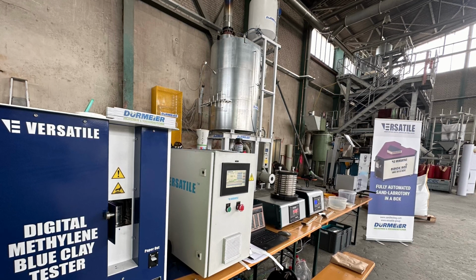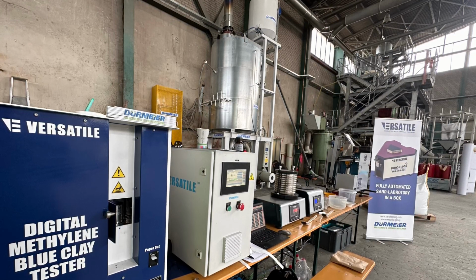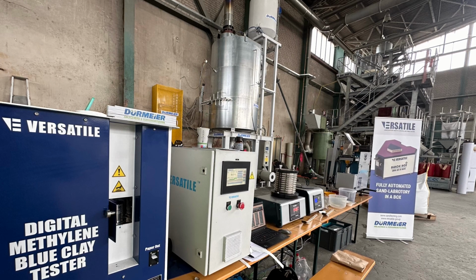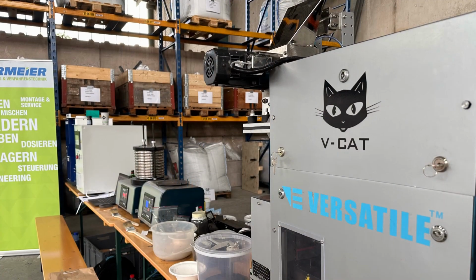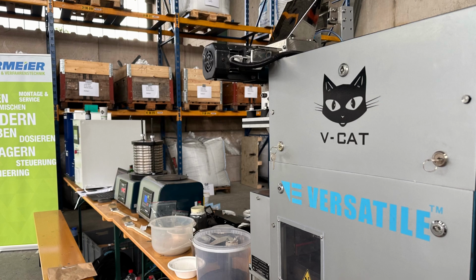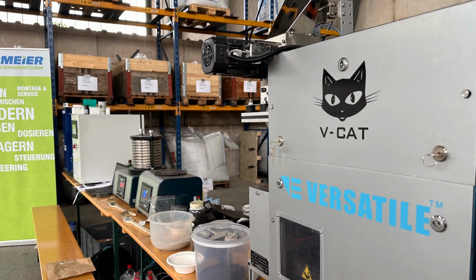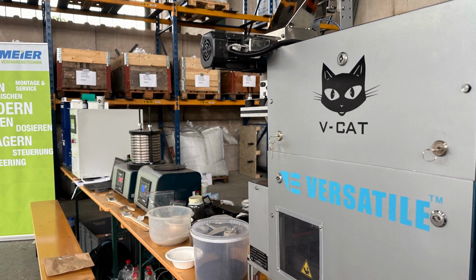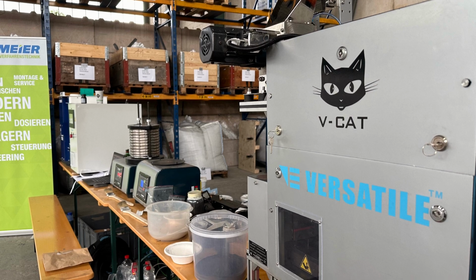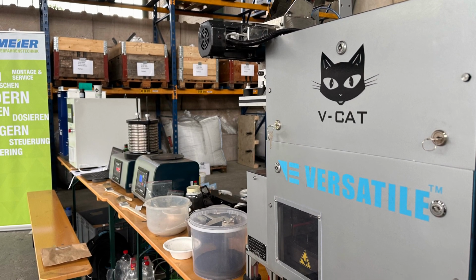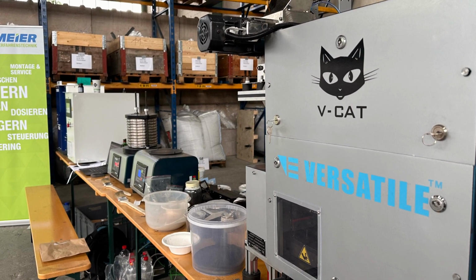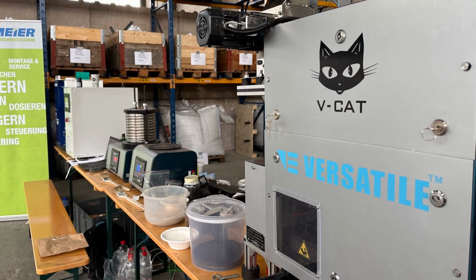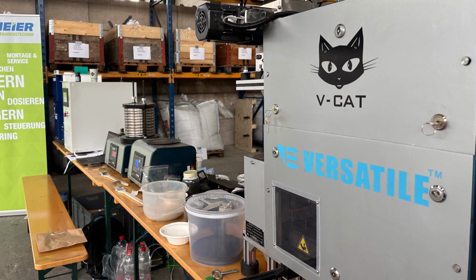Okay. And last one, what about those volatile materials you mentioned earlier? Right. There are tests for volatile material content and also loss on ignition, or LOI. These basically measure how much stuff in the sand mix will burn off or vaporize when it gets really hot. And high values there mean? High values mean potentially more gas generated during casting, which increases the risk of gas-related defects. It's a flag to say, hey, maybe adjust the mix or the additives.